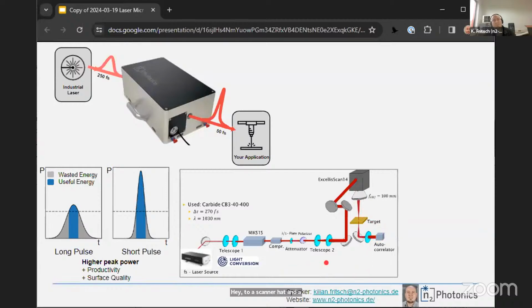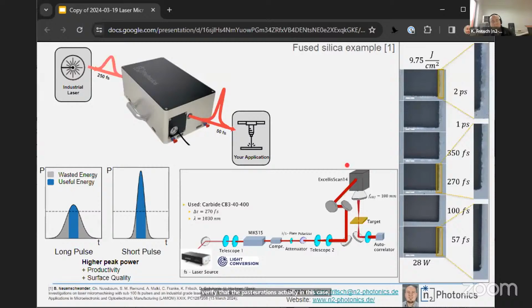The whole commissioning of the system took around 2 days. Why, you would ask, does it take 2 days? Well, the complicated part that we actually performed for our customer was not delivering the 50 femtoseconds right after the laser system. That's the easy part. The challenging part is to do all the dispersion pre-compensation such that the short pulses actually reach the target. And this is what you can see here at the end of the optical chain, a measurement where we verified that the pulse duration is actually, in this case, 57 femtoseconds on the target.